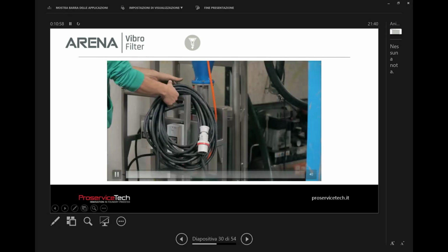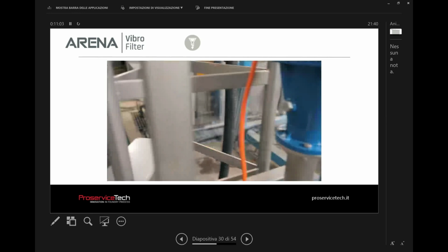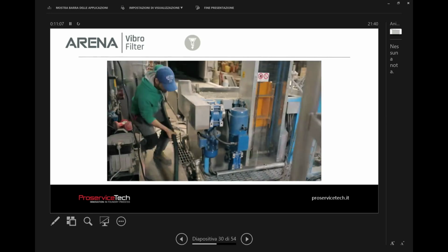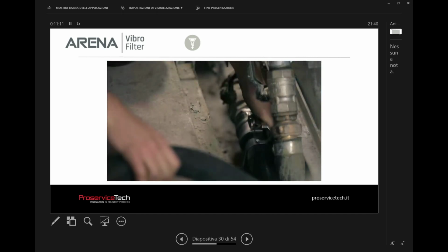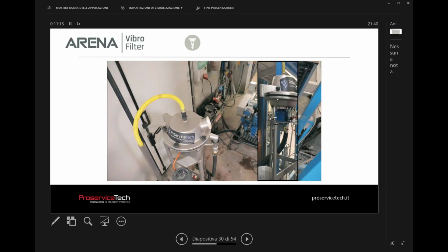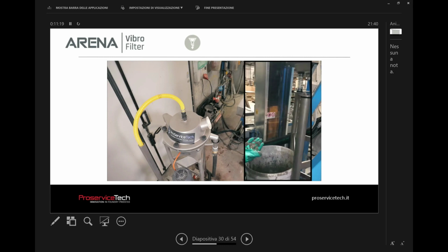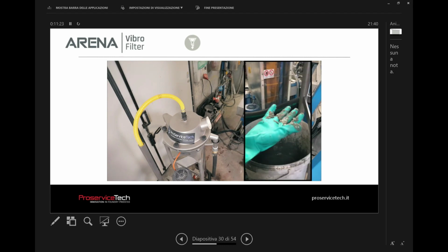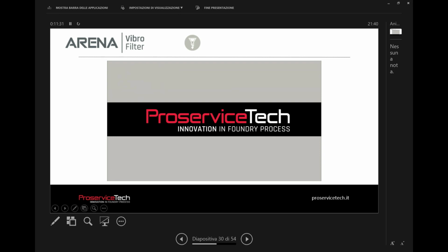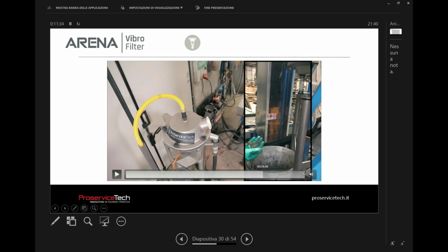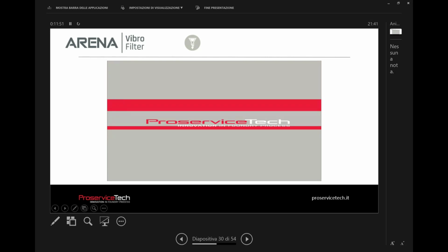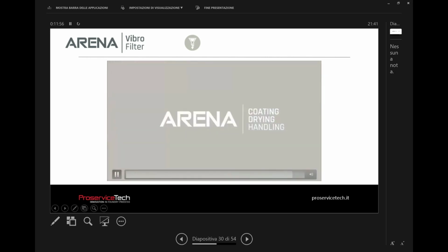It's a movable machine like this, and you connect the fast connector to the dip tank. In this case it's our dip tank, but it can also be your deep tanks. And you let it work for 1 hour. Basically, we have developed this electric pump that works instead of a diaphragm pump. So it's very silent, very efficient, and has a very long life. As you can see, the coating enters here, and from this output the sand particles go out. The other coating enters again into the dip tank. So you can remove even these sand particles.